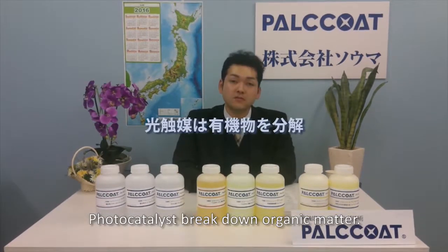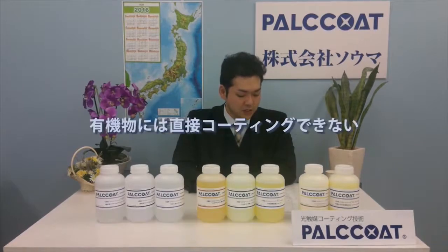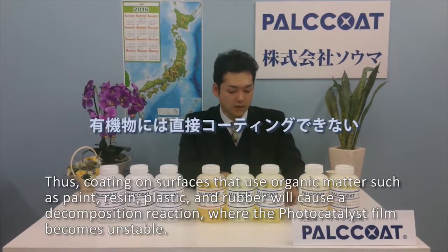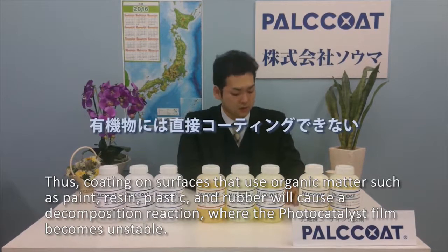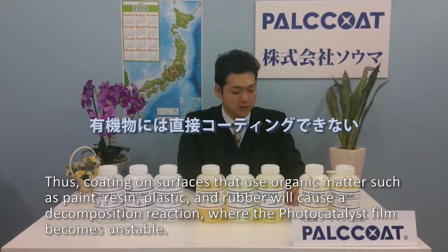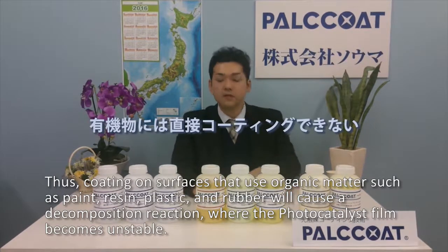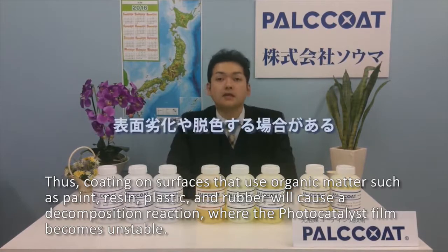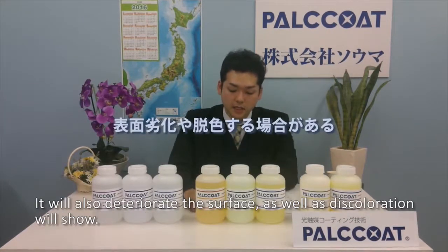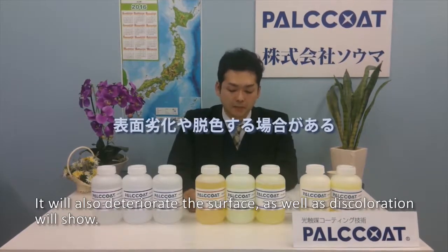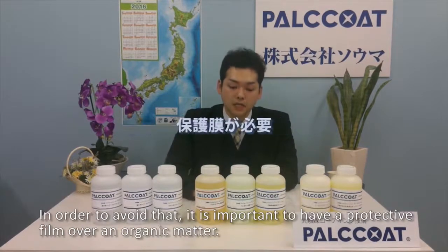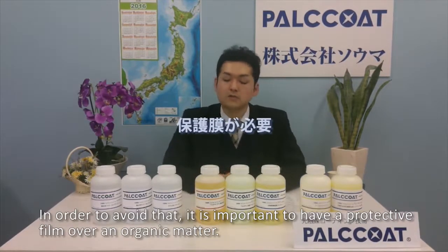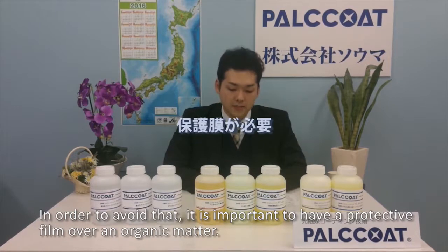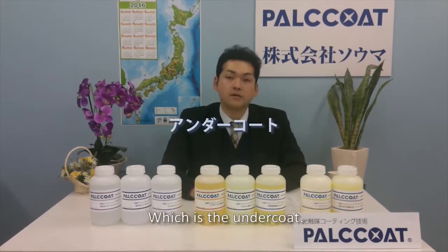Photocatalysts can break down organic matter. Thus, coating on surfaces that use organic matter such as paint, resin, plastic, and rubber will cause a decomposition reaction where the photocatalyst film becomes unstable. It will also deteriorate the surface, and discoloration will show. In order to avoid that, it is important to have a protective film over the organic matter, which is the undercoat.